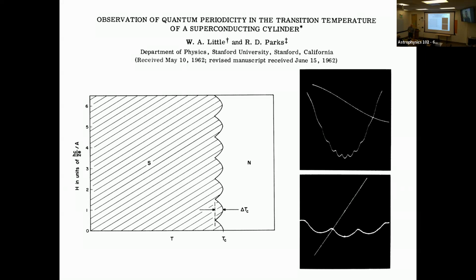There had been some earlier experimental tests from Bill Fairbank, also here, but this was an easy one. This simply said if you measure the critical temperature of superconductivity as a function of the applied magnetic field in a cylindrical shell superconductor, in which you could put flux through the core of the shell, the critical temperature would oscillate, and the period of oscillation would be 1 in units of h/2e. And that 2, that magic 2 in the denominator, was the signature of Cooper pairing.